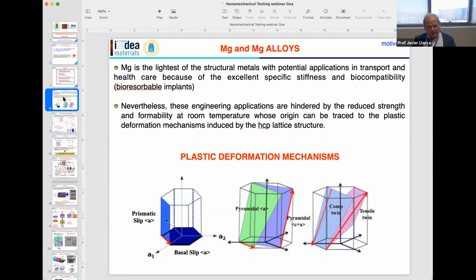So if you look at magnesium alloys and their plastic deformation mechanisms, you have one dominant mechanism, that is basal slip. The critical resolved shear stress for basal slip is very low, but of course basal slip only happens on the basal plane, so it cannot accommodate plastic deformation along the z-axis. To accommodate plastic deformation along the z-axis, you either have to have pyramidal slip in the c plus a direction, or you may have twinning.